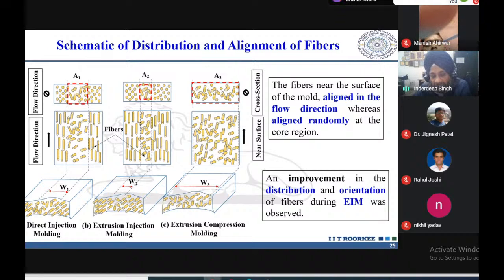So the final summary that we have found out is that an improvement in the distribution and orientation of fibers during the EIM was observed. So EIM, all of you know by now, is extrusion injection molding. So using the extrusion injection molding process, we were able to get better quality, not in terms of the surface finish, but better performance in terms of the mechanical properties of the composites.